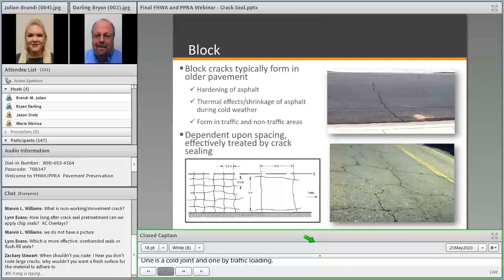Block cracking happens as a pavement ages, and there are some photos here of block cracks. So block cracking gets more and more closely spaced together as pavement gets older. So in this bottom picture, you can see the blocks are almost alligator looking. It almost looks like a fatigued area at this point. And I get asked, would you crack seal this? And my answer would be, it depends. So if you're just going to go in and maybe do some of the larger cracks in here, that might be appropriate. But just to go in and crack seal all of those cracks as a standalone treatment, no, we would not recommend that. There's too high of a crack density on this pavement in this bottom photo.